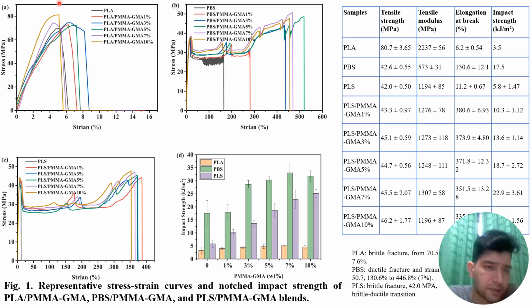the first figure shows the PLA stress-strain curve. Actually, PLA shows a brittle fracture surface, so the tensile property of PLA is improved a little bit, and to some extent, up to 7.6, the elongation at break also increases. Looking at the PBS, the PBS surface is a ductile surface, so the tensile strength improves a little bit, while the elongation at break improves highly, more than 446 percent. It's also improved by introducing the compatibilizer.